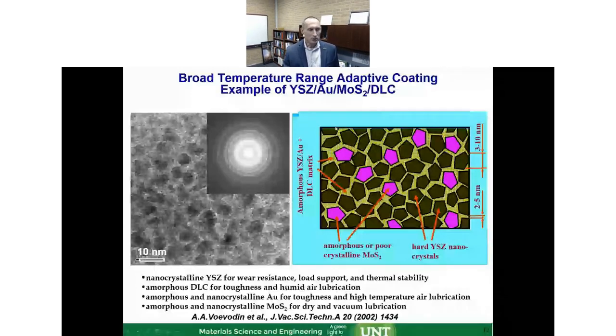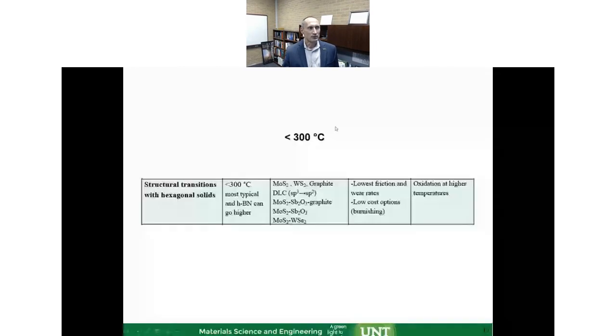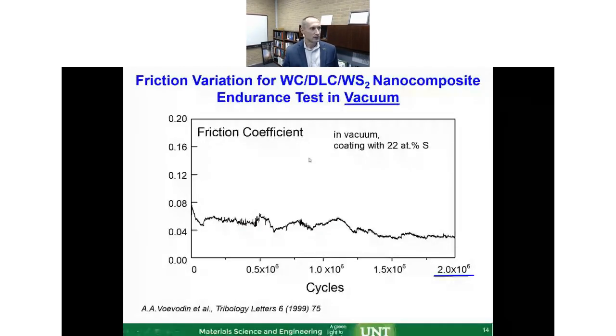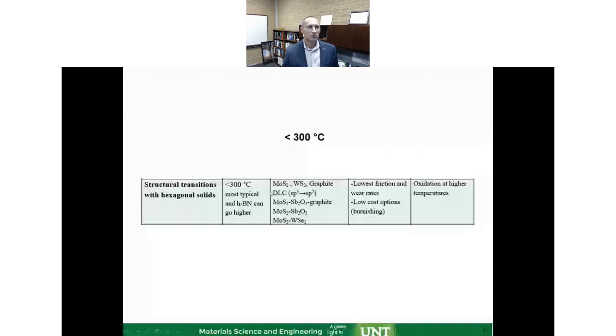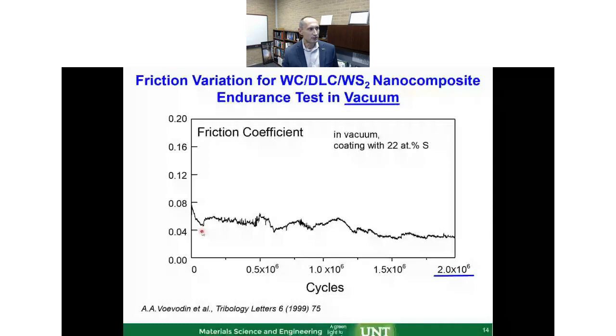But first, let me focus on the low temperature performance of these adaptive coatings. In this regard, let's look at the mechanisms which we can use at 300 C and below. Here we talk about the chalcogenides and graphite. Perhaps hexagonal boron nitride is a sort of exception because it can go to much higher temperatures. But let's focus on this and what the mechanisms are there. We know from a practice perspective that when we do this type of adaptive coatings or lubrication with these materials, we can achieve a very low friction coefficient.